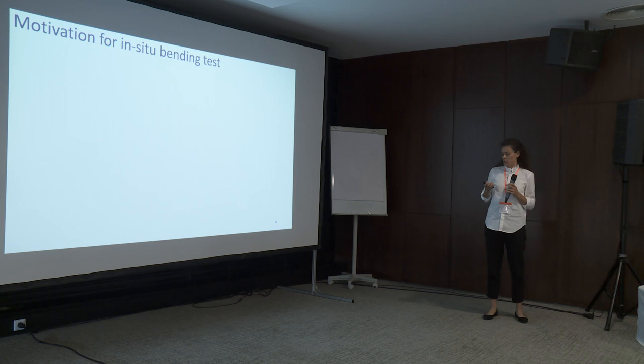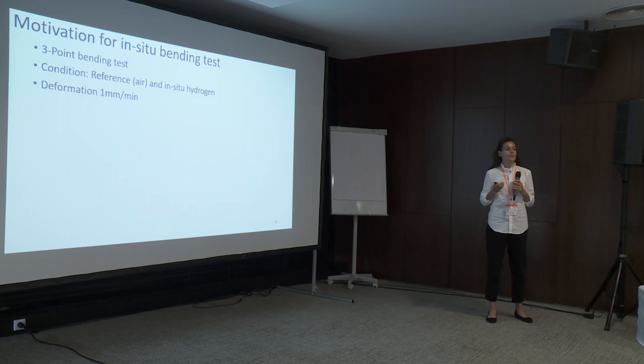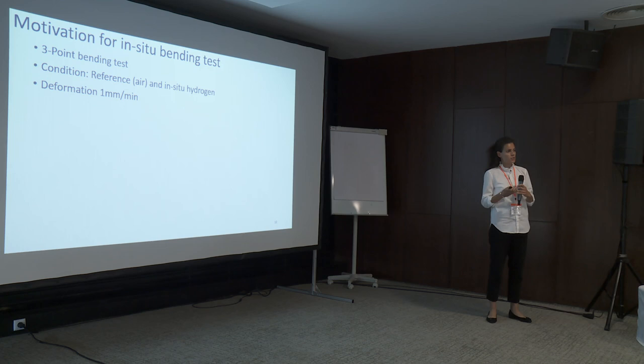The test performed was a three-point bending test under two conditions: one in air without hydrogen to observe the fracture surface, and one with hydrogen in situ. For the hydrogen condition, samples were first charged for two hours to ensure full saturation, then the bending test was conducted continuously with a deformation rate of one millimeter per minute.